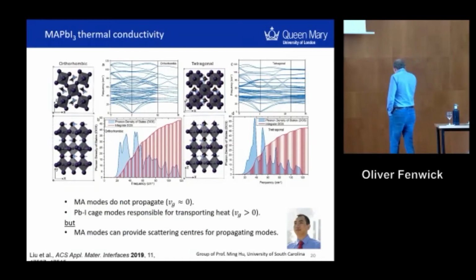One of the questions is, why is the thermal conductivity that we measured in methylammonium lead iodide so low? And so we went to a collaborator, Professor Ming Hu, who's now at the University of South Carolina, and he looked at the phonon density of states. There are a few key points that come out. Methylammonium in the structure can move, it can rattle around, it's very free to move, but there are no propagating phonons that exist on the basis of the methylammonium cations. On the other hand, the lead iodide cage modes are responsible for transporting the heat. They have a group velocity greater than 0. Nonetheless, although they propagate the heat, the motion of the methylammonium can actually scatter the modes that are on the lead iodide cage, and that's what brings down the thermal conductivity.